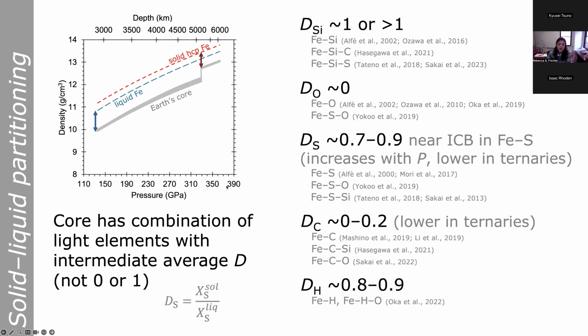So we know the core has some combination of light elements in it that together have some kind of intermediate value for their effective average D. In other words, D can't be zero because there's some light elements in the Earth's inner core. We can see that because the inner core is less dense than solid iron. But D also can't be 1, because that would mean the elements have no preference for solid versus liquid. And we know that's not true because, based on density, there's more light elements in the outer core than